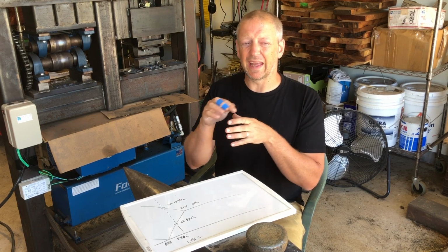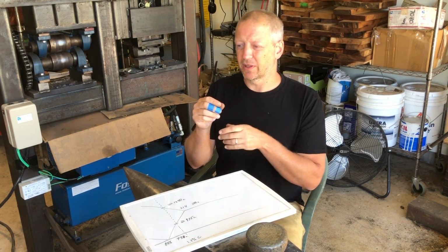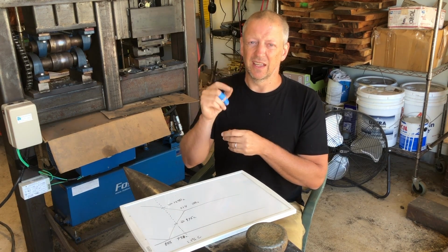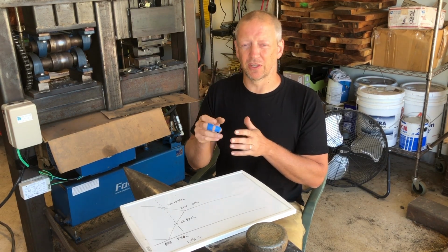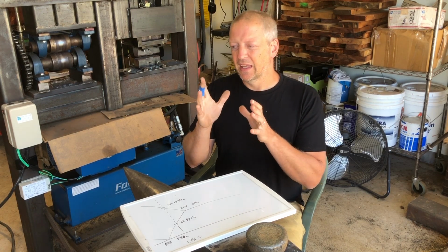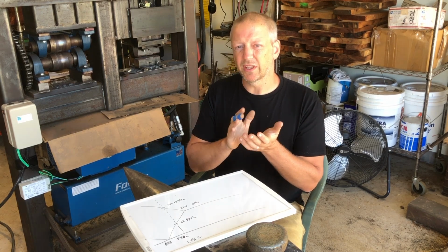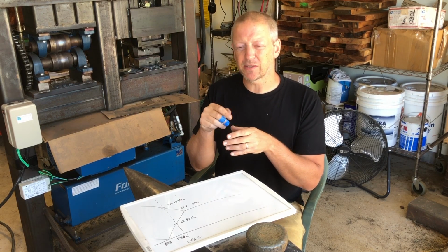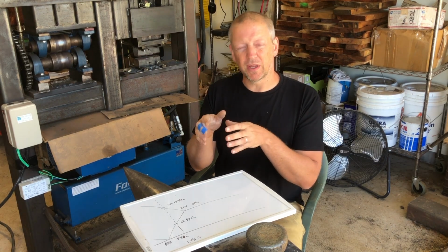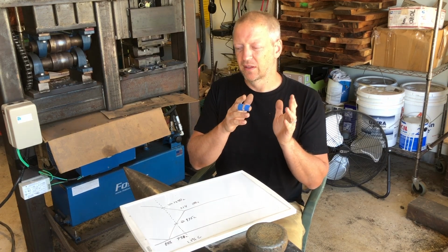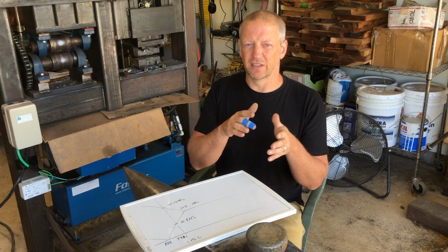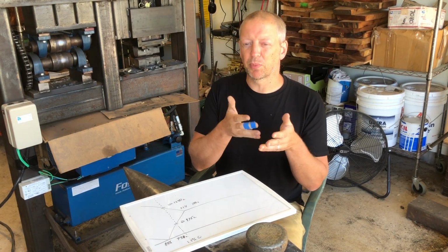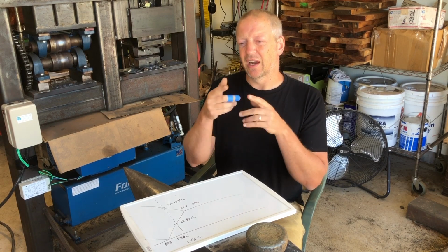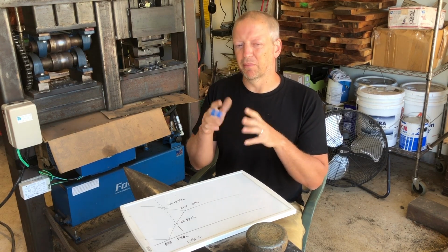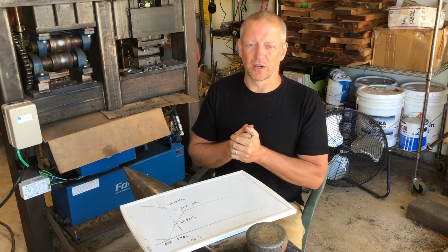However, if you look at that grain boundary carbide, you'll realize that the grain structure in the ingot is huge, absolutely enormous. And we really don't want that. Another aspect that is troublesome is that the grain boundaries probably still follow fairly closely with the dendritic structure, that solidification structure. So if there were imperfections in that solidification, our grain boundaries probably still align with them fairly well, and that makes for a pretty weak structure overall.